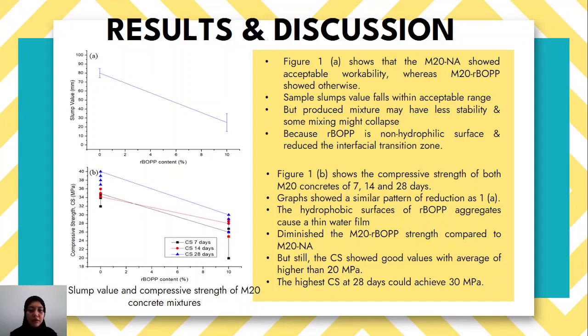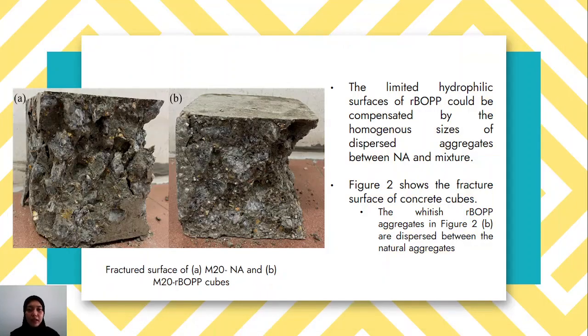The hydrophobic surface of RBOPP aggregates causes a thin water film, diminishing the M20 RBOPP strength compared to M20 NA, but the compressive strength still showed good values, with an average higher than 20 MPa. The highest CS at 28 days could achieve 30 MPa. The limited hydrophilic surface of RBOPP could be compensated by the homogeneous size of dispersed aggregate between NA and the mixture. Figure 2 shows the fracture surface of concrete cubes. The whitish RBOPP aggregates in 2B are dispersed between the natural aggregates.